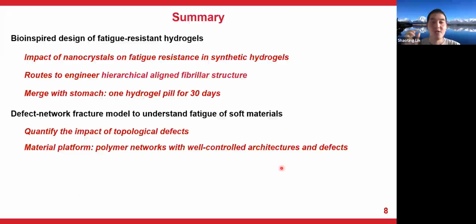So to summarize, we learned the design strategy from nature inspiration. We provide the first experimental evidence to show the impact of nanocrystals on fatigue resistance in synthetic hydrogels. We also provide multiple routes to engineer hierarchical aligned fiber structure, including mechanical training and 3D printing. We also successfully demonstrated one application as ingestible hydrogel pills for long-term physiological signal monitoring. And beyond the material design and fabrication, we're also trying to push the fundamental understanding of fatigue of softer materials. We propose a defect network fracture model to quantify the impact of topological defects. And from the experimental side, intense efforts have mostly focused on randomly cross-linked networks. So here we show the potential of using an ideal network as a material platform with well-controlled architectures and defects.